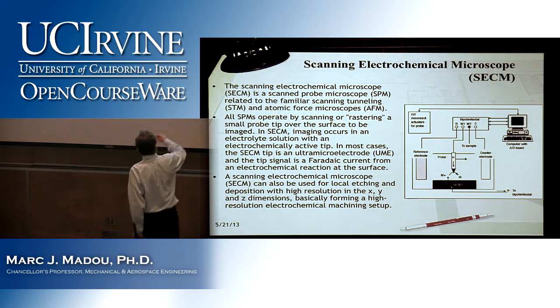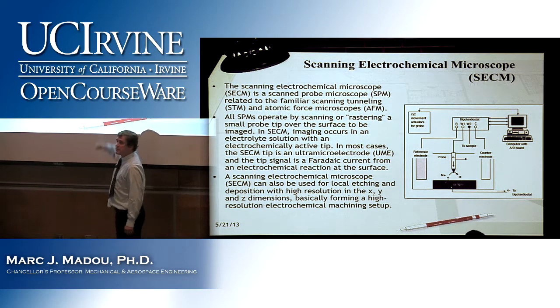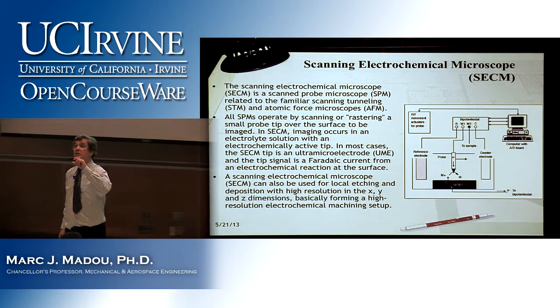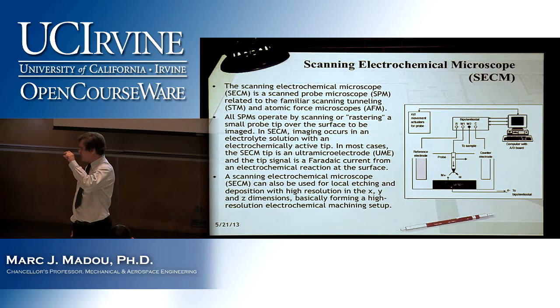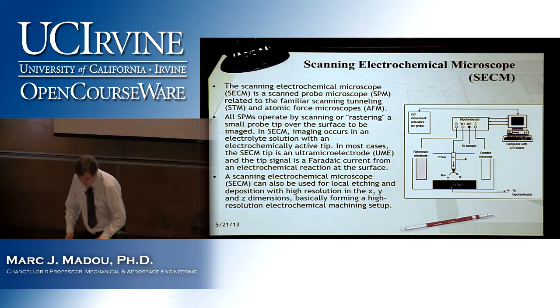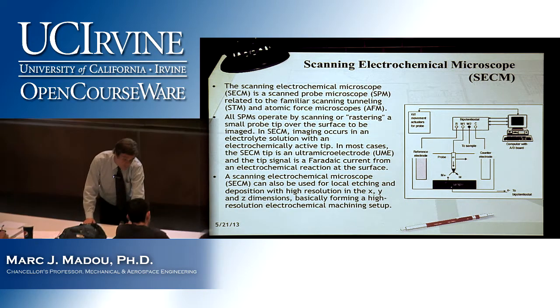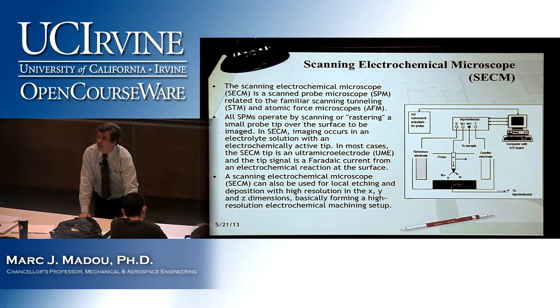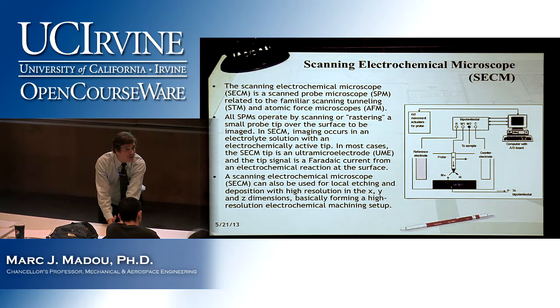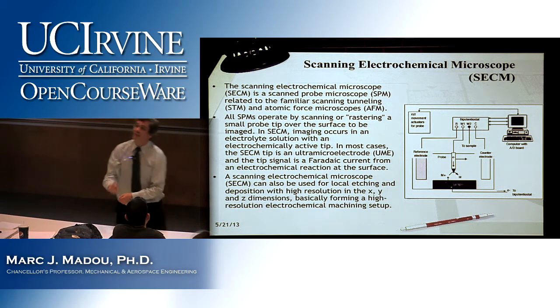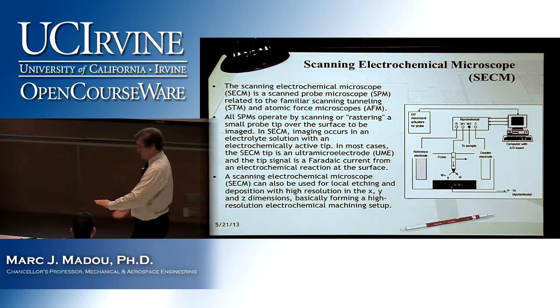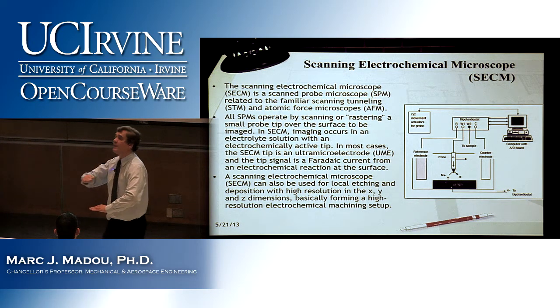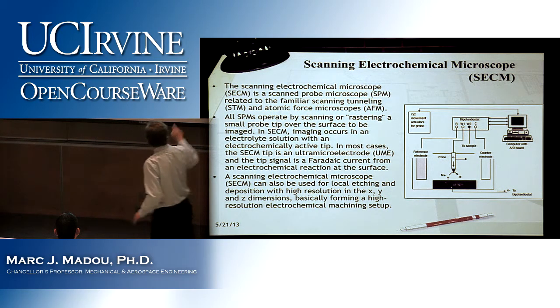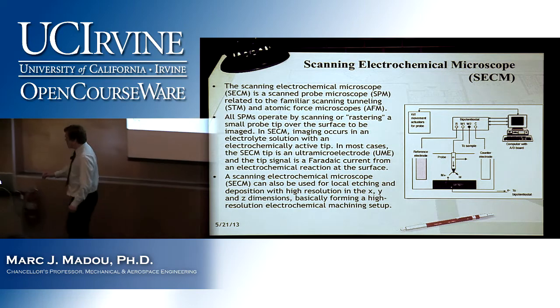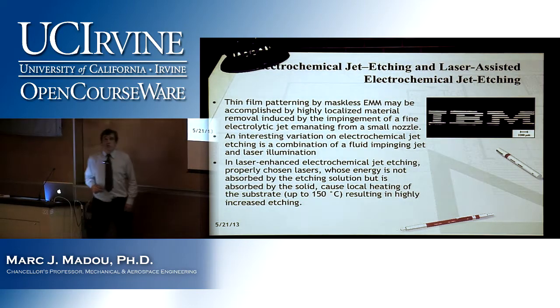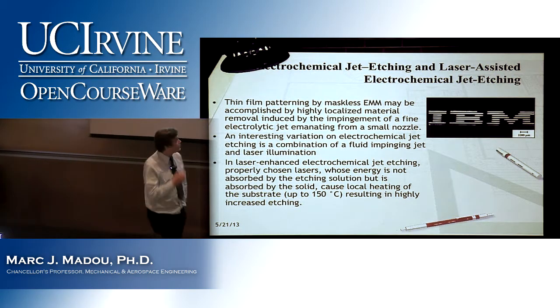Why is that? Because in this case, the current between the tip and the surface is quantum mechanical tunneling, and so the current size is extremely dependent on the distance. It's an exponential curve. That's back to that control loop: if my probe by accident, instead of 2 microns away from the surface, is 1 micron away, the current shoots up by a factor of 100. That is a tremendous feedback to the piezoelectric: oh, pull back. Remove yourself over 1 micron to always keep the same current. So that is that controlled feedback, and that's exactly what you do in all of these scanning probe microscopy techniques. I will introduce 2 more electrochemical techniques before quitting for today.